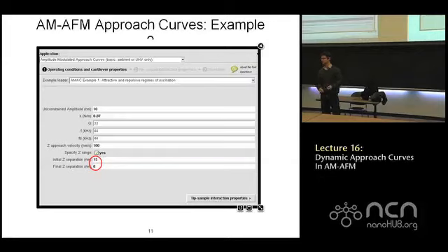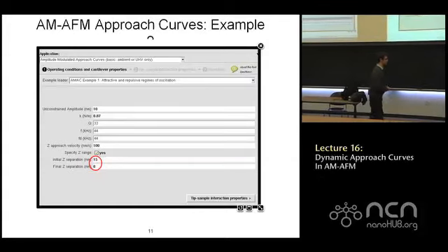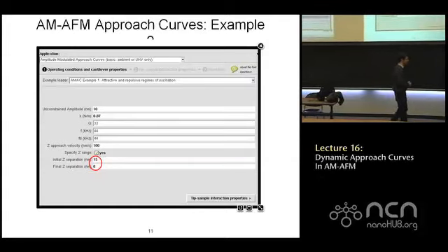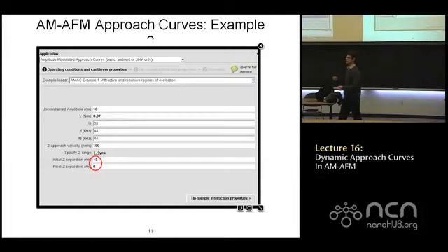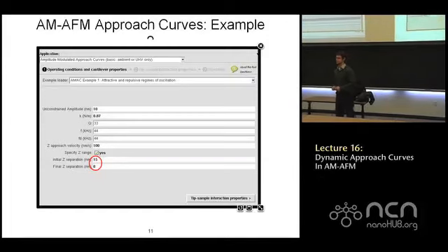It's better when we're imaging and having very small changes in the Z position, but not when we're sweeping over 100 nanometers or something very quickly. But if you have a closed loop Z piezo, that's much better. Under that, if you do the static force distance curve and the simulation and finagle the parameters a little bit, then you should feel pretty good about that part of it. So, okay.